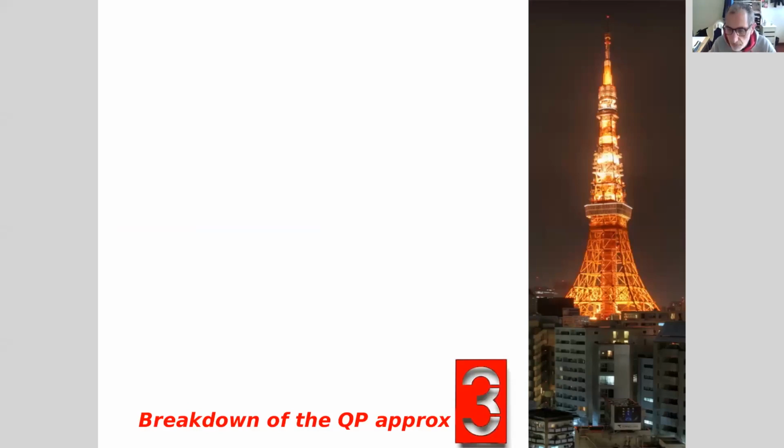Okay, so I will go just through this, to give you an idea of something that, in my understanding, is a peculiar difference between the electronic correlation and the phononic correlation. Even without knowing anything about many-body theory, you can intuitively see that phonons have a much lower energy compared to electrons in a semiconductor. In general, the phonon energy can be evaluated with the Debye energy, that is the energy of the maximum phonon frequency. In silicon it's 60 millielectron volt. It can be 100, can be 200 millielectron volt, but in general it's much lower than the gap.